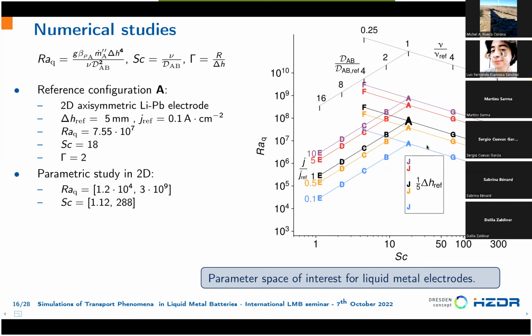And as discussed before, we expect to see 2 regimes, and we find out that the regime change takes place at the flux Rayleigh number of 3 times 10 to the 5. So we have a high Rayleigh number regime in light green here and a low Rayleigh number regime in dark green here. And we will first look at the high Rayleigh number regime and how it evolves in time.